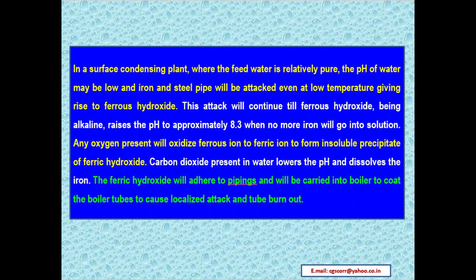In a surface condensing plant, where the feed water is relatively pure, the pH of water may be low, and iron and steel pipe will be attacked even at low temperature, giving rise to ferrous hydroxide. This attack will continue till ferrous hydroxide, being alkaline, raises the pH to approximately 8.3, when no more iron will go into solution.